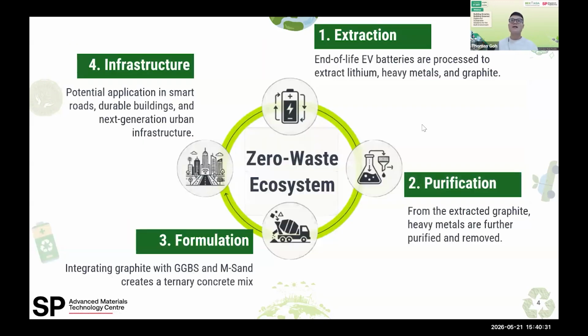Okay, so under this zero waste system, how it works is that first, from the battery supplier point of view, there will be an extensive extraction and purification of the battery. This is to decommission the battery to prevent battery explosion. So they have to treat it first. They have to fully discharge the battery first, for example in a concentrated salt solution, to prevent the explosion. After that, they will dismantle it. Then they will separate the respective metal components and plastic components. Subsequently, they will extract the lithium, the heavy metals, and lastly, the graphite.